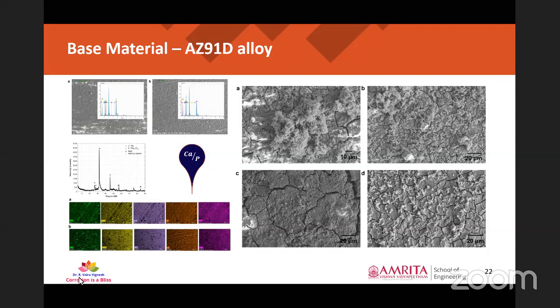So you can just see A is after first day, B is after 3 days, C is after 5th day, and D is after 7th day. Initially flower-like clusters bloomed over the entire surface, then it eventually fell off from the surface. That is, it just dissolved into the solution completely after 5 days. And then after 7th day, there is a complete formation of corrosion product layer over the specimen that is immersed for 7 days. So we thought of analyzing the corrosion products first.